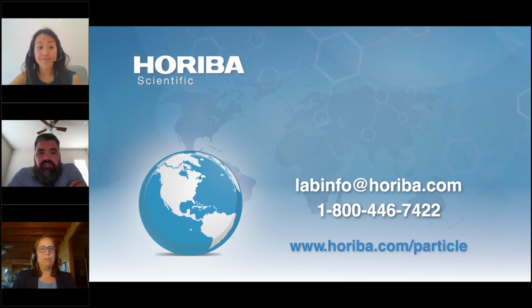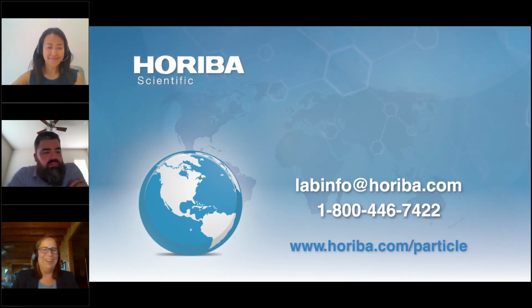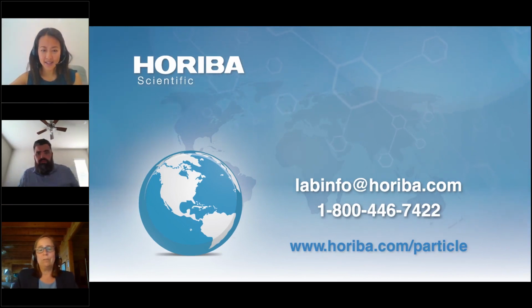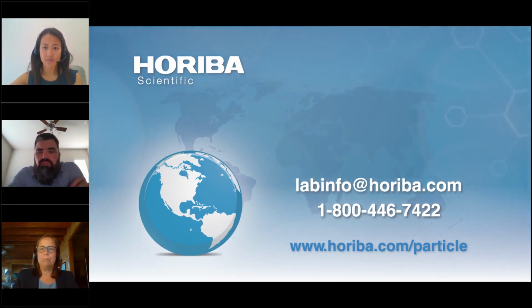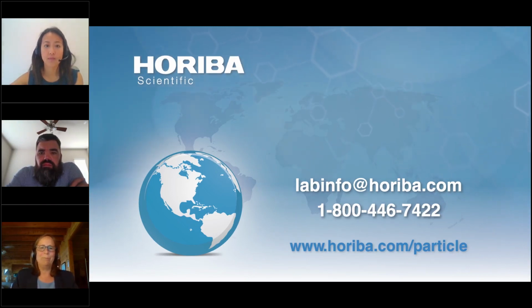Just jumping in there, because obviously I have particle experience too. If you have an aqueous solution and a VLP, the index of refraction is just too similar. It's the image contrast. This is an imaging microscopy experiment, and the contrast you can get between the solution and the particle is so small. It can be challenging, but I think there are ways to tackle that with fluorescence, if you can tag them. The benefit is having untagged samples, so that may not be a solution. This is a really good question because this is around the same size as AAV.